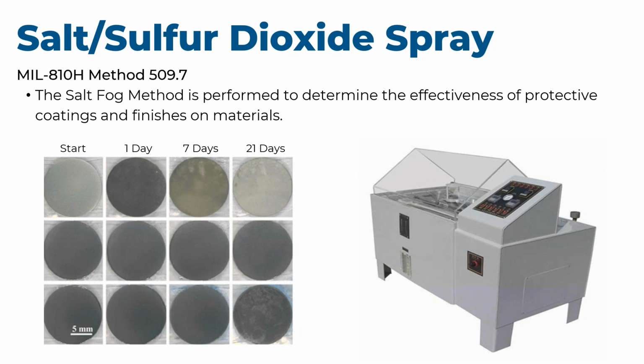Another aggressive test that comes into play, obviously, with military optics, optics used at sea, optics used in avionic applications, is salt and sulfur dioxide spray. So basically, you have a chamber and you have salt and sulfur dioxide in a mixture, and it's introduced into the environment, and essentially your coated optics sit there. There are 1-day tests, 7-day tests, and 21-day tests. Obviously, the longer the duration, the more aggressive the test is.